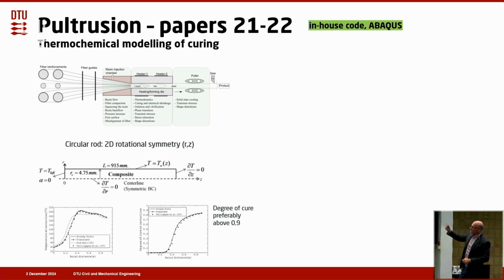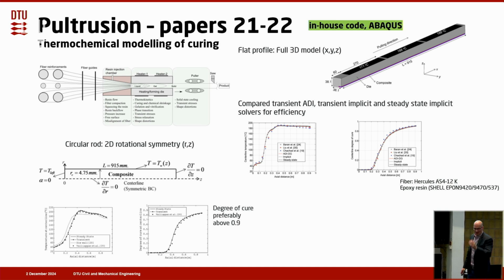So we started with a simple 2D rotational symmetrical model where we found the centerline temperature as a function of distance as well as the degree of cure. And the degree of cure, it's how hardened it has been. That has to be around 0.9 or higher. Then we continued with comparing some different solvers from literature, ADI, transient, implicit, steady state, and so forth and so on, to see what was the most efficient seen from a computational viewpoint.